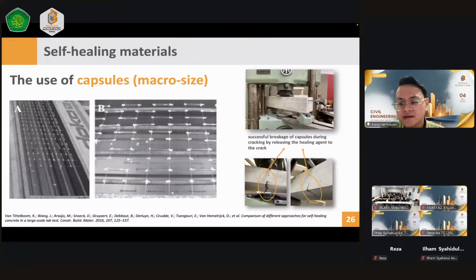And this is also an example from my research. We also showcase the successful breakage of the capsules after the cracking, by releasing the sealing agent or the healing agent into the cracks. You see, there was a wet formation at the bottom of the specimen, and this indicates the sealing agent is flowing through the cracks.